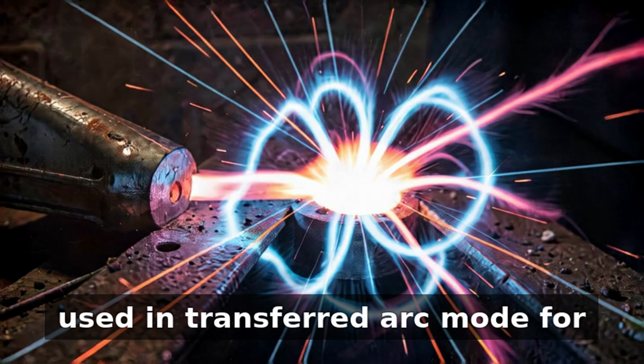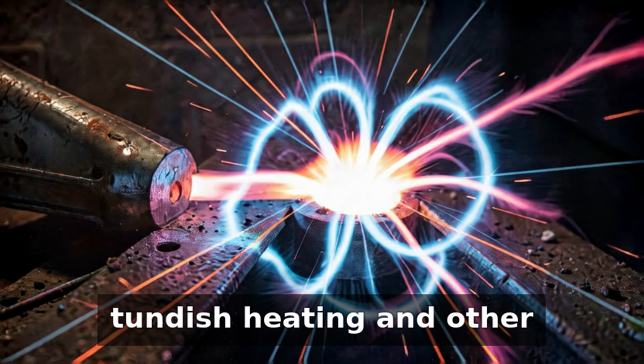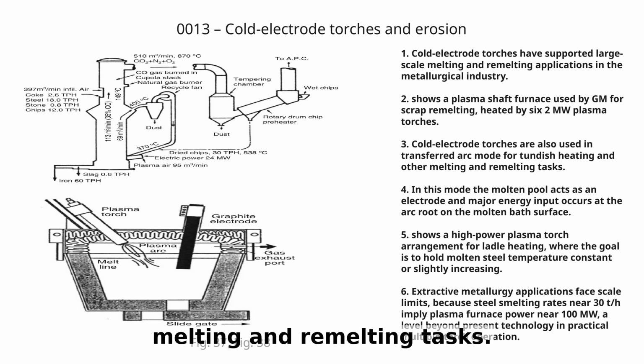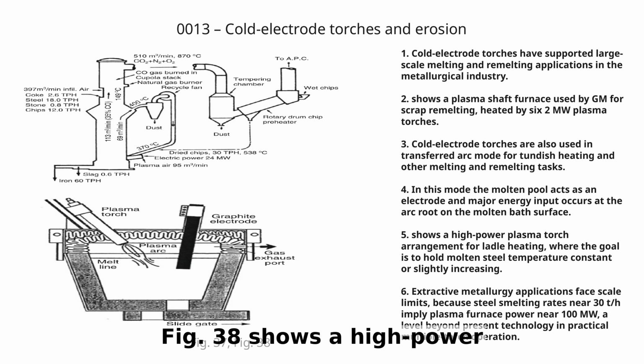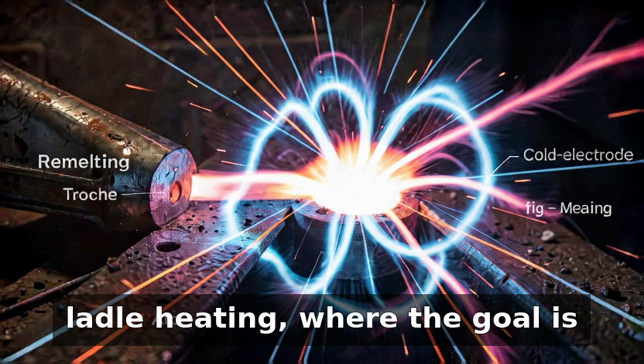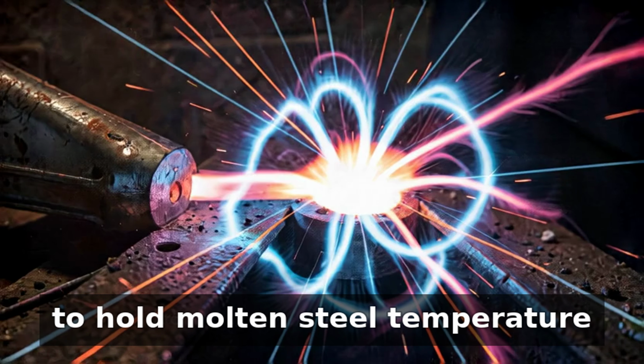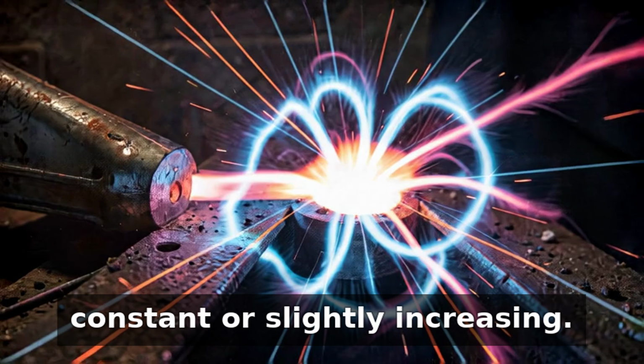Cold electrode torches are also used in transferred arc mode for tundish heating and other melting and remelting tasks. In this mode, the molten pool acts as an electrode and major energy input occurs at the arc route on the molten bath surface. Figure 38 shows a high-power plasma torch arrangement for ladle heating, where the goal is to hold molten steel temperature constant or slightly increasing.